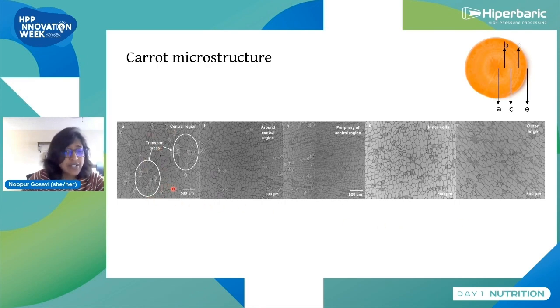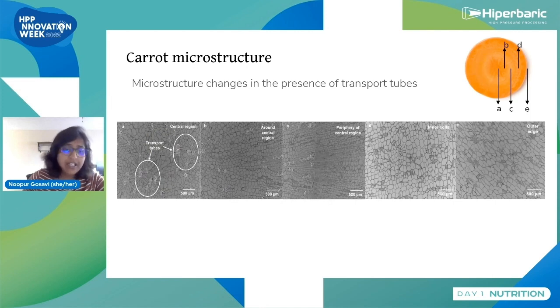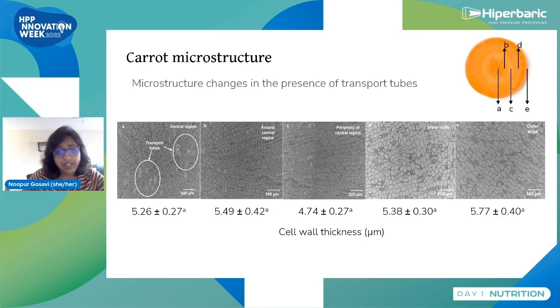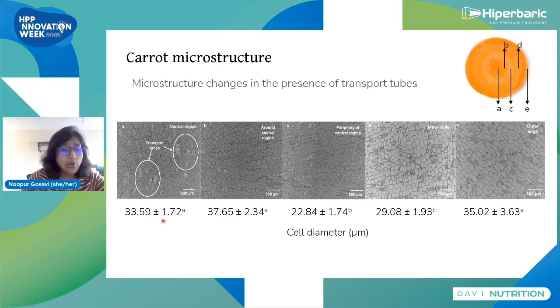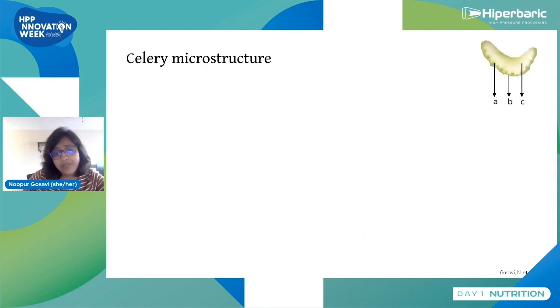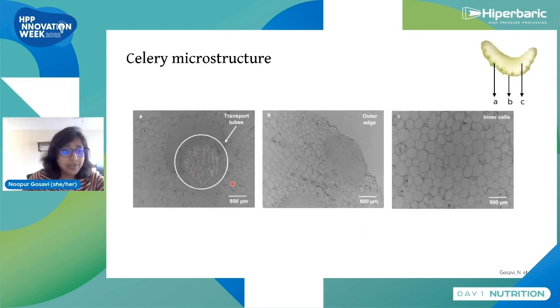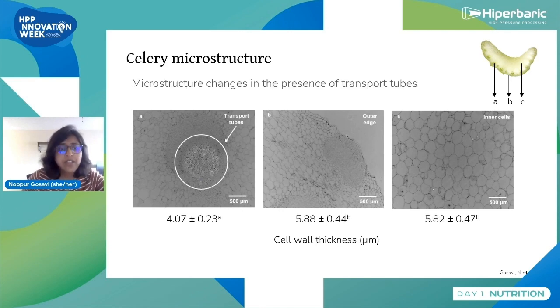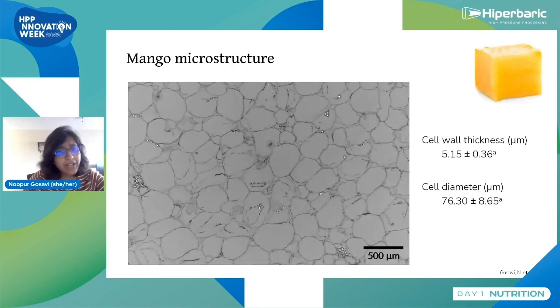At the very center, you see these transport tubes, which are responsible for transporting nutrients. And you notice that because of the transport tubes, the microstructure is very different. The cell wall thickness is not as different between the different images, but the cell diameter goes down towards the middle of the baby carrot and then goes back up. Similar observations are for celery, where there are transport tubes around the edge, which are bigger, but the cells around it are smaller, and then their size increases again. So the transport tubes cause changes, and we'll see that the cell wall thickness is similar, but the cell diameter vastly varies. For mango, because there are no transport tubes, you'll see that there is no variation.